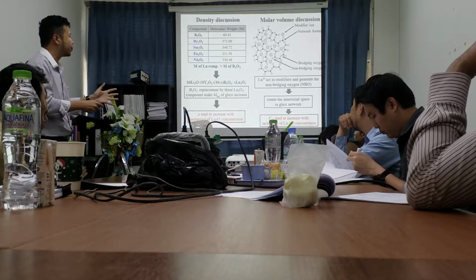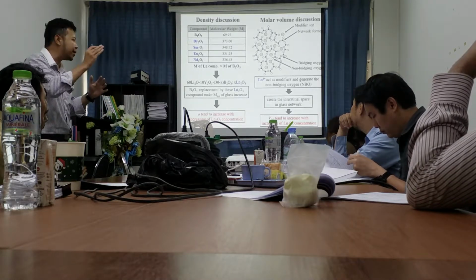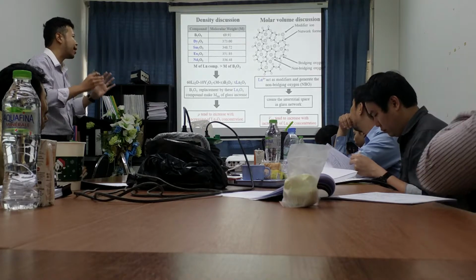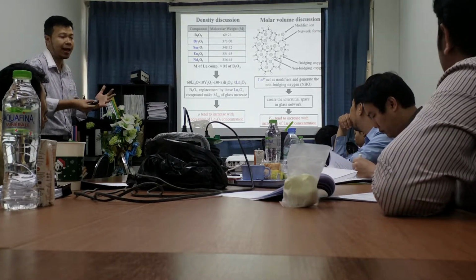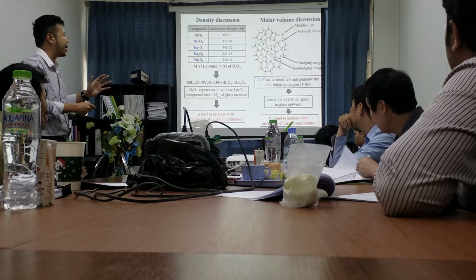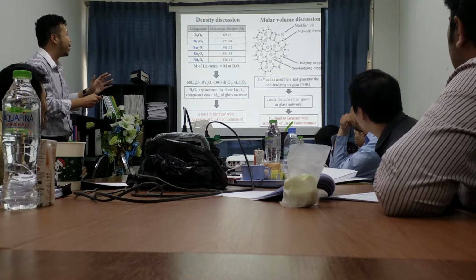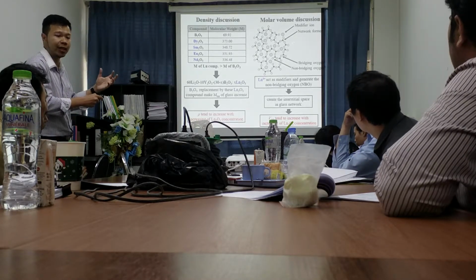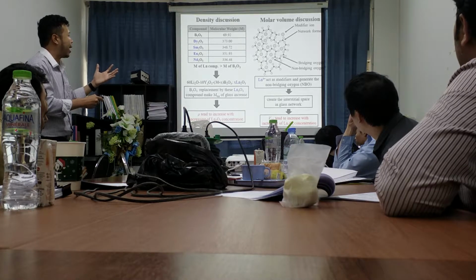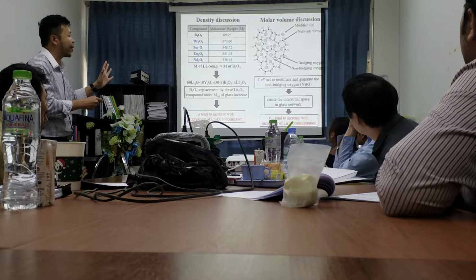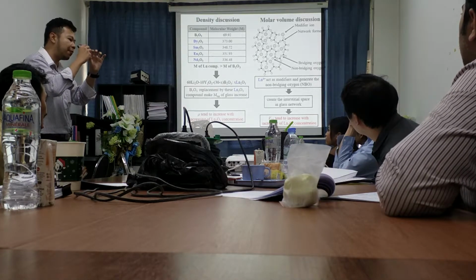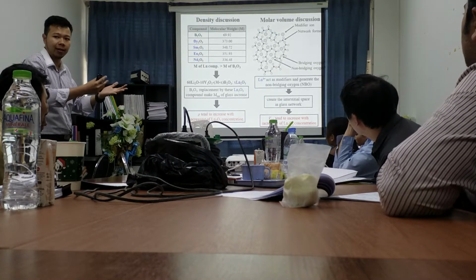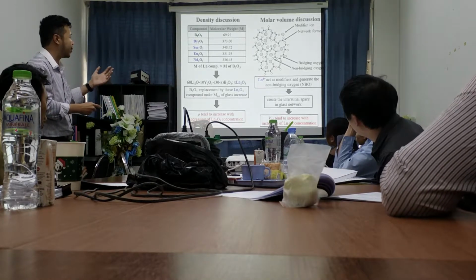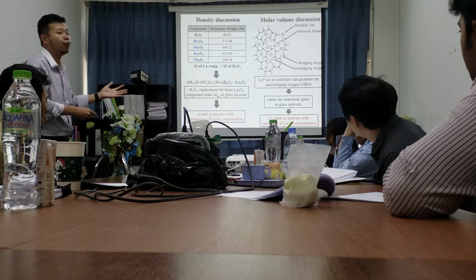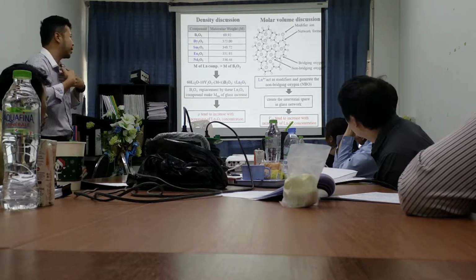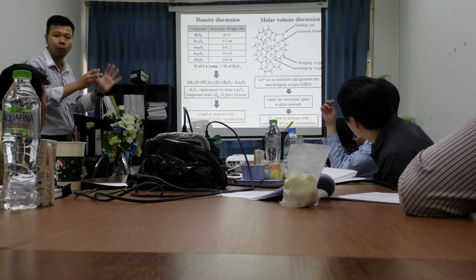For the molar volume, the molar volume increases with increasing lanthanide oxide concentration. We can say that the lanthanide ions act as modifiers, and modifiers destroy the oxygen bridging in the glass network, and it creates space because some bonding is destroyed. It generates more space, more volume. This is my explanation about the density and molar volume.